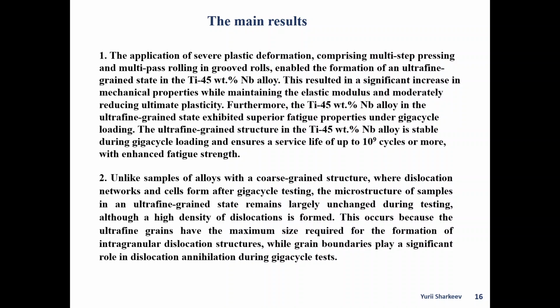Second, unlike samples of alloys with a coarse-grained structure, where dislocation networks and cells form after gigacycle tests, the microstructure of samples in an ultrafine grain state remains largely unchanged during testing, although a high density of dislocations is formed. This occurs because the ultrafine grains are smaller than the size required for the formation of intragranular dislocation structures, while grain boundaries play a significant role in dislocation annihilation during gigacycle tests.